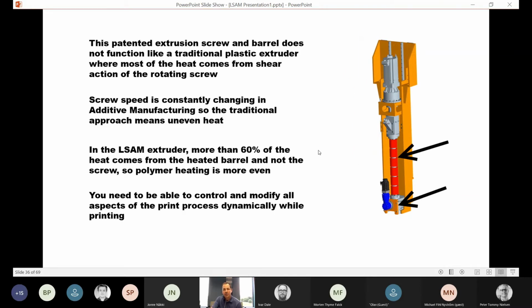The patented extrusion screw and barrel does not function like a traditional plastic extruder, where most of the heat comes from the shearing action of the rotating screw. The screw speed is constantly changing in additive manufacturing, so the traditional approach means uneven heat. In the LSAM extruder, more than 60% of the heat comes from the heated barrel and not the screw, so polymer heating is more even.